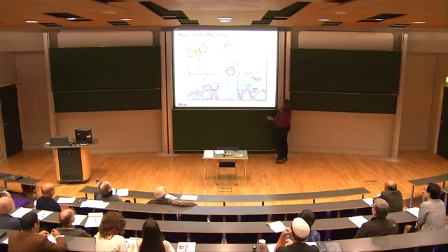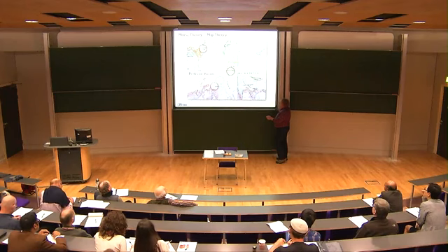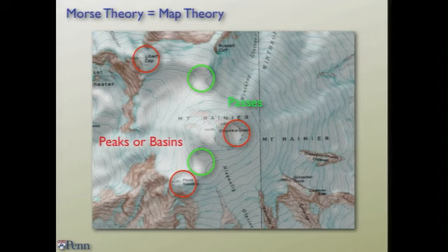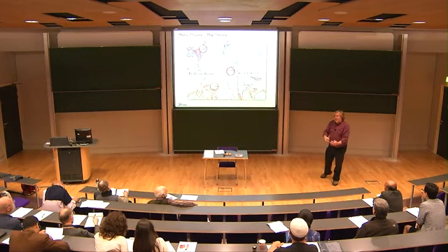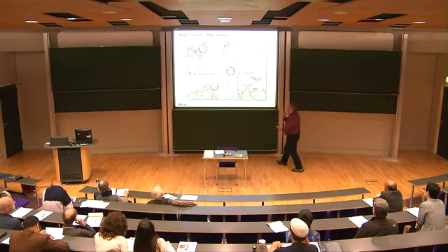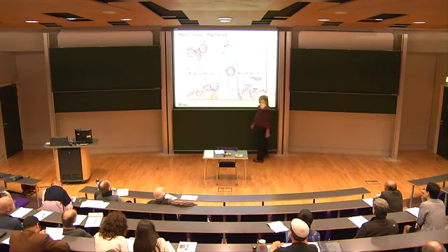So what happens is you always trap a pass. And look at a pass. A pass is actually a -1 disclination. So if you try to bring two +1s together, you always trap a -1 with you. And so you can't actually make a +2 point defect. You can't put a mountain on a mountain.